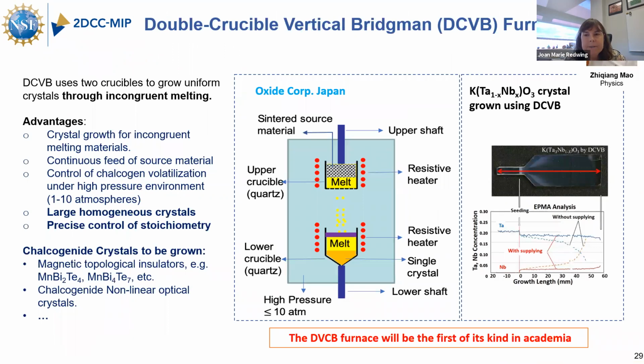In the bulk crystal growth facility, Zhiqiang Mao is going to be adding a double crucible vertical Bridgman system. So the Bridgman technique is a process commonly used for bulk crystal growth of materials that melt congruently. So that's the case where the melt and the solid composition are the same as you go through the phase transformation. However, many materials of interest melt incongruently. And that means that the melt composition is going to change over time as the crystallization occurs. And that can cause problems in obtaining homogeneous crystals.